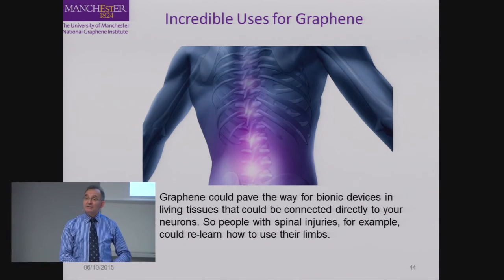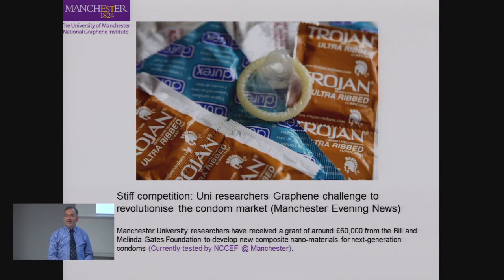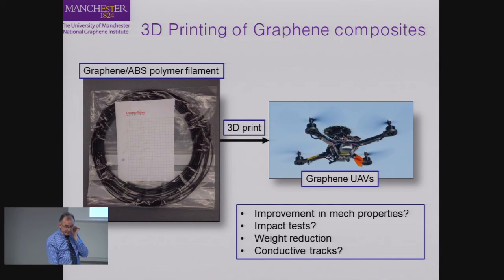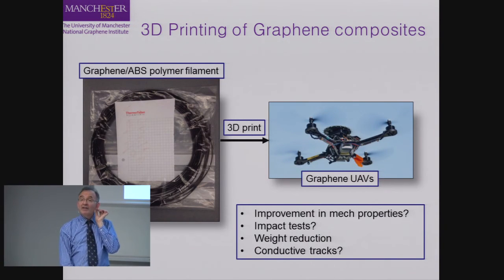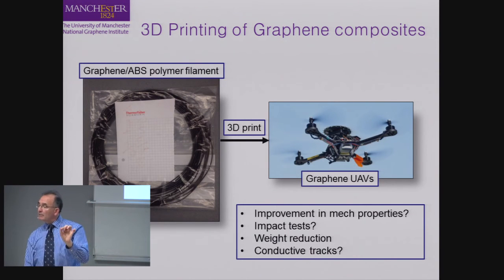It can be used for applications in bioengineering. This is a project funded by the Bill and Melinda Gates Foundation, where the objective of that project is to develop graphene condoms, that they don't burst as easily as the commercially available ones. It's a big issue in Africa. Again, the difficulty there is on the dispersion, but we're getting there. 3D printing of graphene composites. If you look at currently 3D printing, it's all monolithic materials with no reinforcement. Maybe this is an area where actually graphene can be applied more easily.